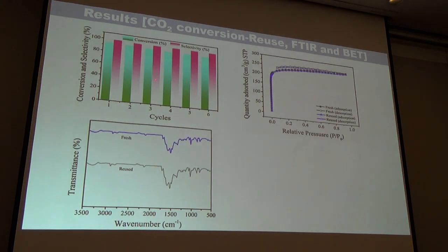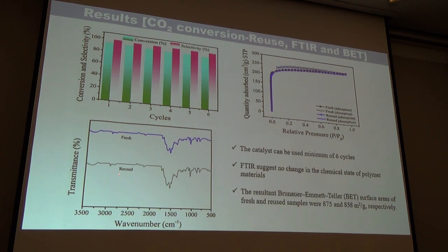And further, the reusability of the catalyst was also tested. As you can see, the catalyst can be used for a minimum of 6 cycles. The reused catalyst was also tested by FTIR and BET analysis. The FTIR suggests no change in the chemical nature of the polymer, as well as the BET surface area suggests there is no change in the pore structure of the polymer material.